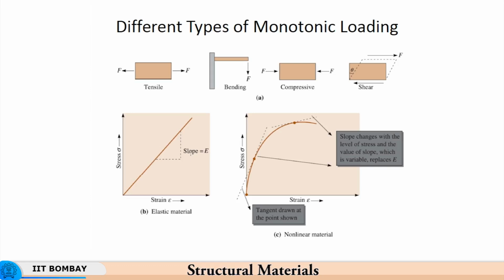Therefore, if you take steel for instance, irrespective of the variation in the chemical composition, as long as it is a ferrous material, an iron based alloy, the Young's modulus does not vary too much. It remains practically constant. The difference between the Young's moduli of aluminum and steel is because of the equilibrium distance between the two, and the shape of the interpotential curve that is responsible for many of the observed properties, and we have seen that in many of the previous lectures.